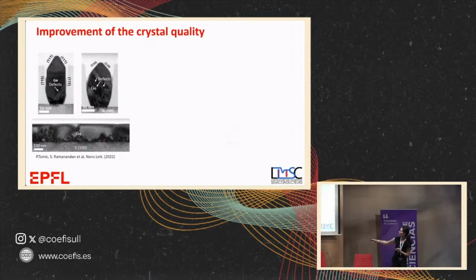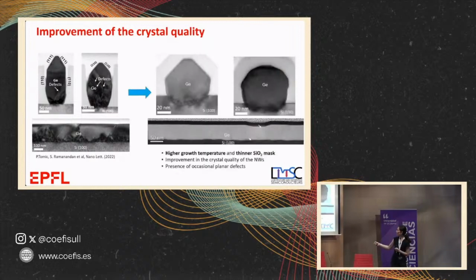If I look here, we made a very thick oxide because we were thinking that the dislocations would get oxide, a defect. That's why we mask here. But why don't we try a very thin mask and play with the temperature, see if we just get rid of the dislocation by just cooking them and allowing the atoms to achieve the more relaxed state. When we do this, so here you don't even see the oxide, and we play with the temperature, you see that we have something at the interface, but we have the whole wire that is much smaller and defect-free. So playing with the materials, we are able to obtain very, very high-quality materials.